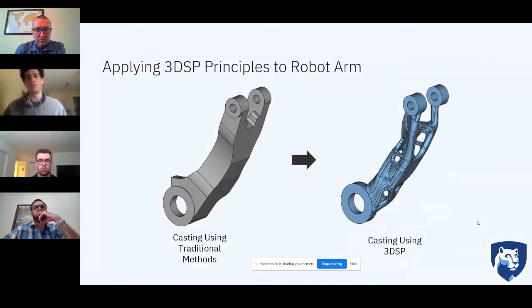So as Ryan alluded to, he primarily gave an overview of the different things we can use 3D sand printing for to optimize our system. So the idea behind this was we were already going to need to print out the robotic arm casting. And so if we were already going to do that, why wouldn't we print a novel rigging geometry for it so we could get the highest quality casting possible, rather than just throw on your standard straight sprue, straight runner, and just cylindrical risers. So with that in mind, we took this casting and then started designing a conical helix sprue as well as novel spherical risers so that we could get the highest quality casting possible.